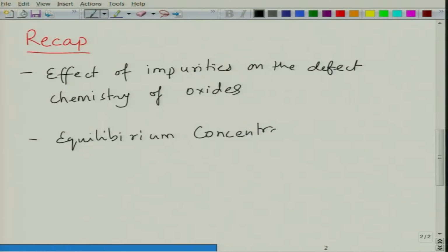So we just took a very basic thermodynamic route to calculate the defect concentration. We looked at the change in the free energy when you consider vacancies and the host atoms as two different entities, and depending upon the configurational entropy and the enthalpy balance between the two, you get changes in the free energy.